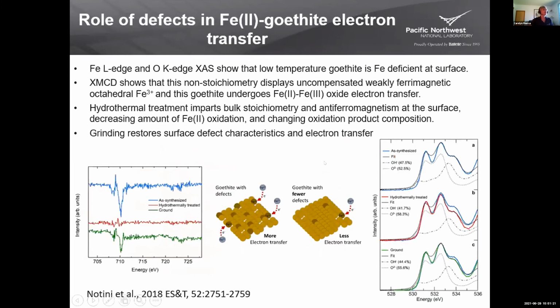So the first example of this is looking at goethite. Computational chemistry suggested that iron 2-3 electron transfer is kinetically inhibited if you have a pristine goethite surface, and so we did some experiments to demonstrate that with Michelle Scherer and Luisa Notini, where they produced goethite using a low temperature method, and we showed from XMCD that this had a slight magnetic signal, which was due to iron defects at the surface, and that this defective goethite could undergo electron transfer reactions with iron 2 at the surface. But when you anneal the goethite and you remove those defects, then you don't get that electron transfer.